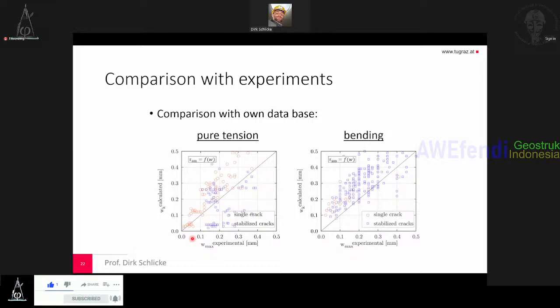Sure. It's no overestimation. This is an experimental crack width, and experimental crack width means not that you have the theoretical possible maximum crack width. This is already subject to scatter. So of course you have a maximum crack width in your experiment, but this does not mean it's the maximum crack width you can obtain in the worst condition. So maybe here you have already some relief of crack width due to scatter. But when we calculate, we really calculate the maximum possible crack width. So actually you should not look that everything is on one line. We only need to check that everything is on this side of the diagram. This is then the prediction idea.